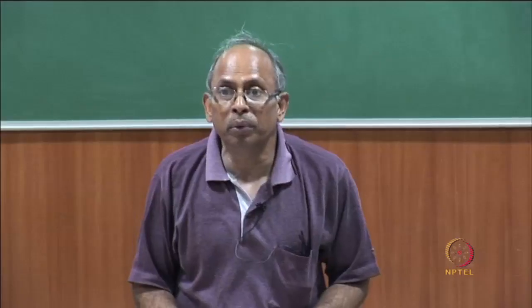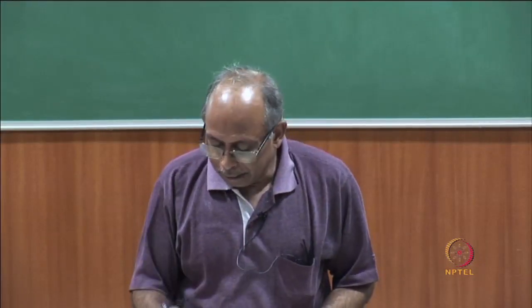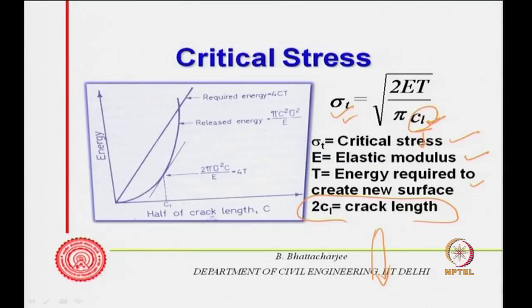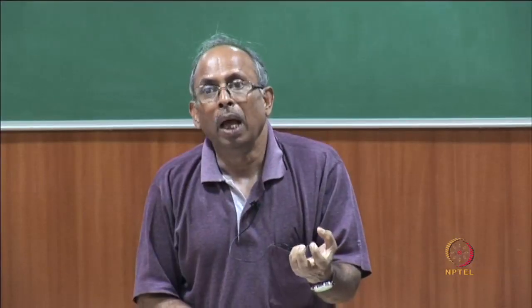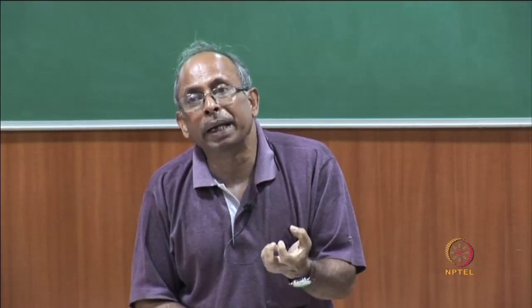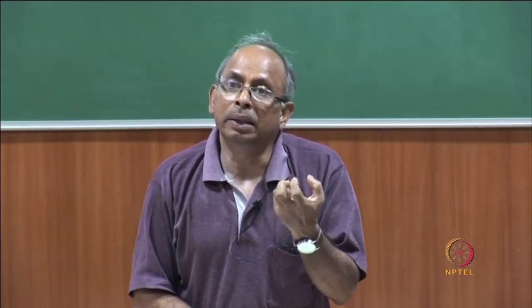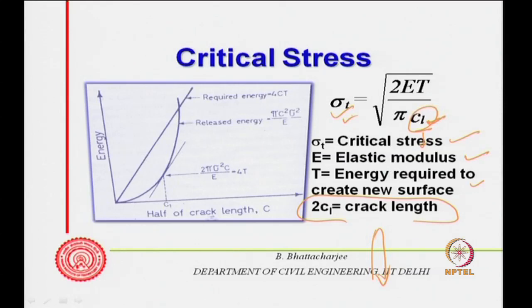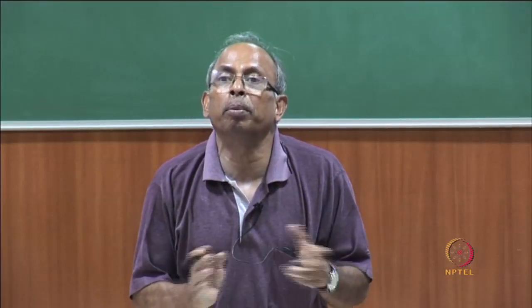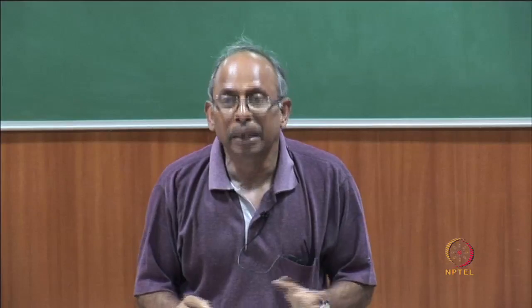So, if some holes already exist, the larger their dimensions, the lower the critical stress. Fracture will start propagating from them at some stress, that is sigma t.